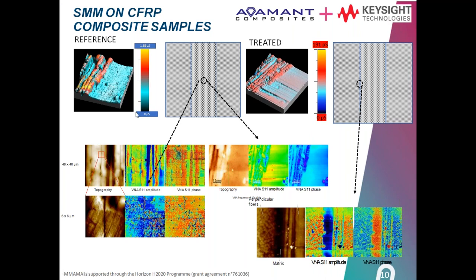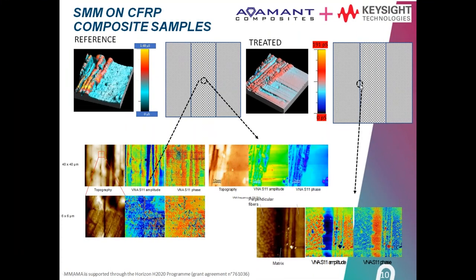The difference that we can see is mainly that fibers usually are conductive, but the matrix around the fibers is an insulator. So what we are trying to see is how we improve conductivity in the matrix area. But what's very important for us is the interface between two consecutive layers. And that's work that we have started to do now, and we are happy to see some nice first results.